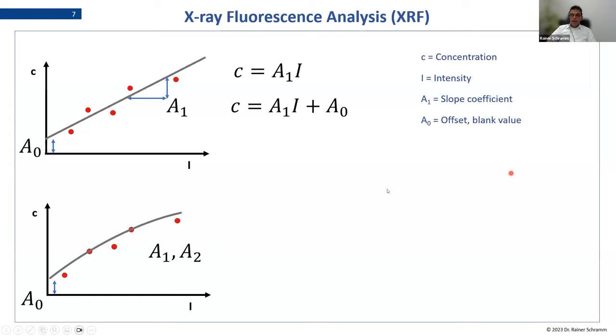In some rare cases, we could also see a quadratic dependency. For example, if you have a constant matrix like a liquid and you have a trace element inside this liquid and the trace element is getting higher and higher in concentration, we will see that there starts some self-absorption and then the relationship becomes quadratic.